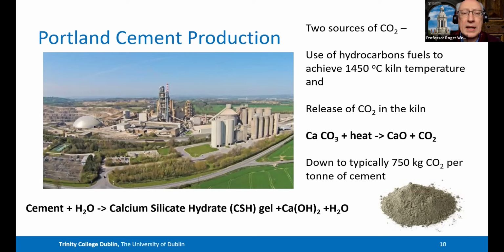And that's principally because alternative fuels have been able to be used. And that obviously needs to be expanded still, but there's been great progress. And we should recognize that progress in trying to address this problem. The process of what happens when you add water to cement is chemically very complex, but it can be summed up in this very simple equation, which I'm sure you're all familiar with. But in essence, when you add water to cement, you create a glue, which is the CSH gel, and there's a byproduct, which is calcium hydroxide.